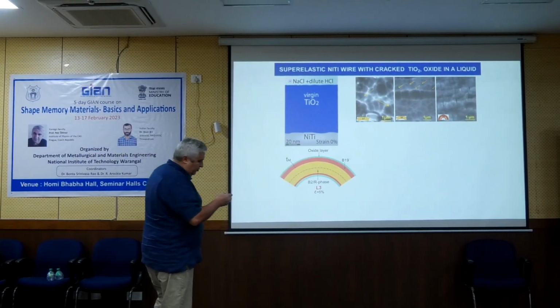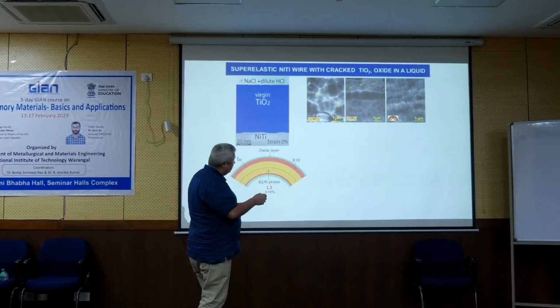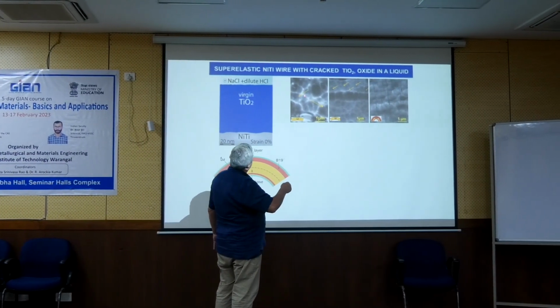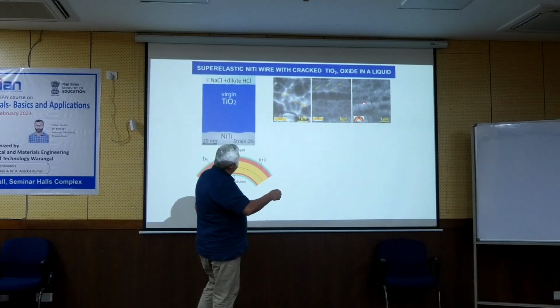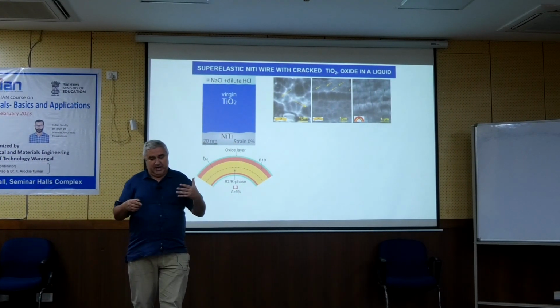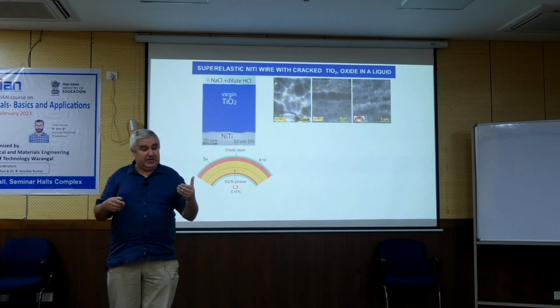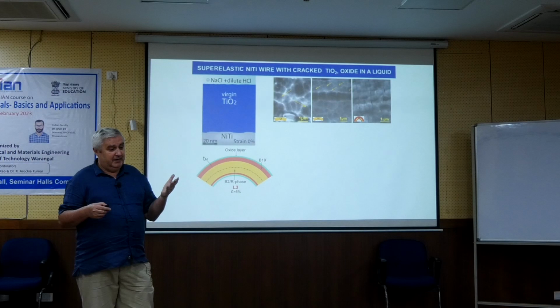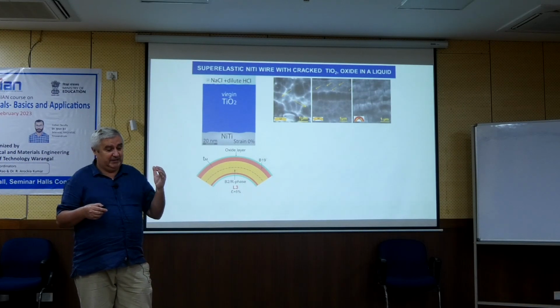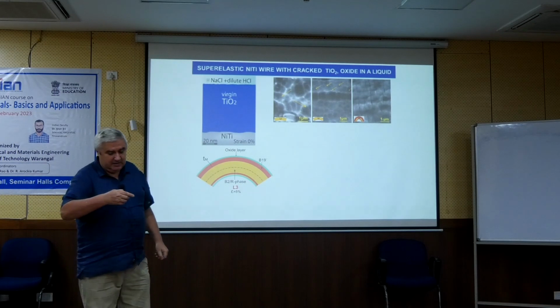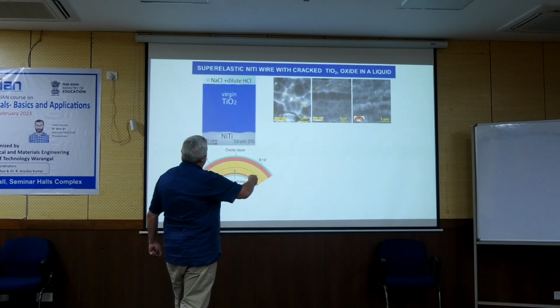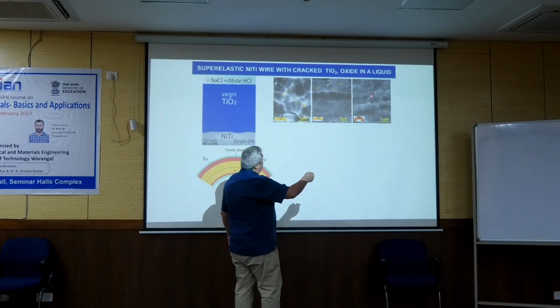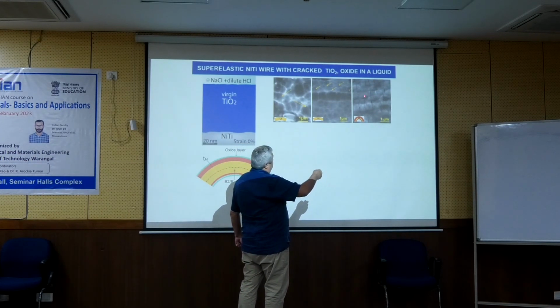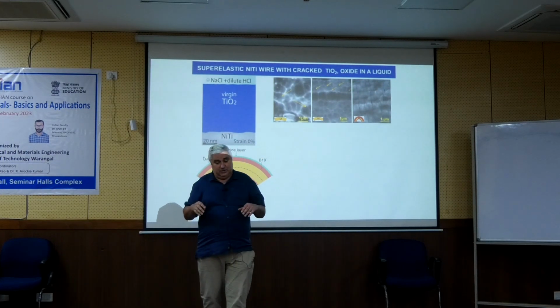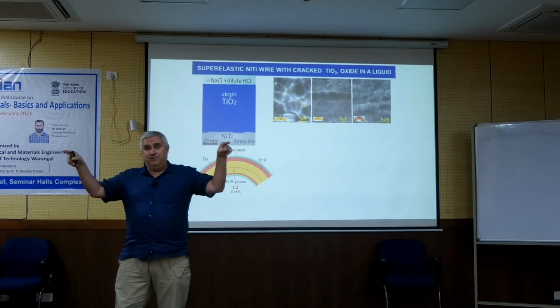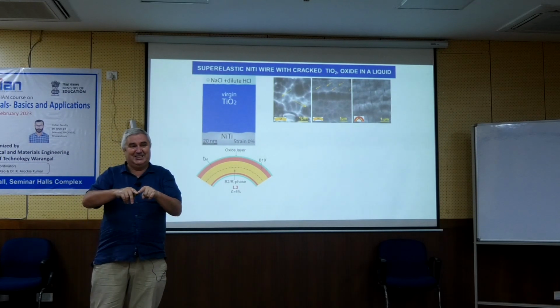I have to jump here. When we look on the nitinol, which had surface oxide basically uncontrolled, something like 150 nanometers thick, after one superelastic cycle, when we look at it with high resolution SEM, we found that there are cracks in this oxide. And everybody who is doing the corrosion knows that if you have the surface with some kind of crack in the oxide, this is a problem.